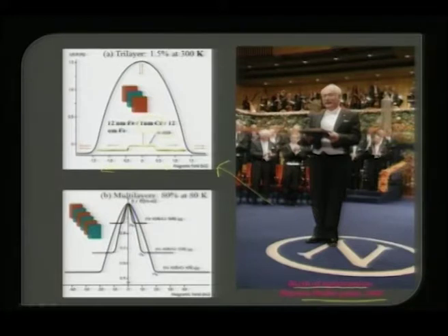Whereas if you separate the same thickness of iron, dividing it as 12 nanometer of iron, and put one single small layer of chromium, only 1 nanometer, then you can clearly see this same feature is now more pronounced.